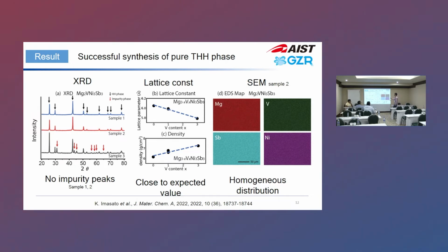So this is XRD, and as we discussed, these peaks are clean enough. We don't see any impurity peaks, and I believe this is a single phase. But sometimes you lose some magnesium and get some nickel antimony impurities, so you have to think about the synthesis route as well. The other reason I believe they have this composition is that the lattice constant changes linearly with vanadium content. So these are the end member compositions, magnesium 1-1-1 compositions. You can see the density and lattice parameter change linearly. I think this is enough to believe we have a single phase.